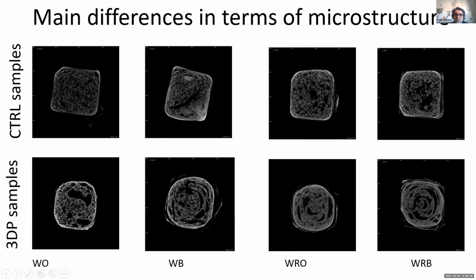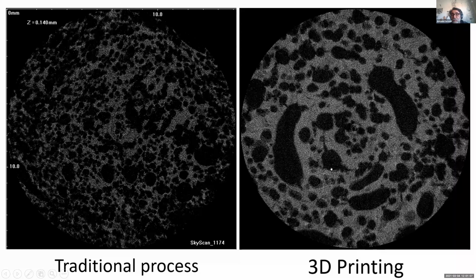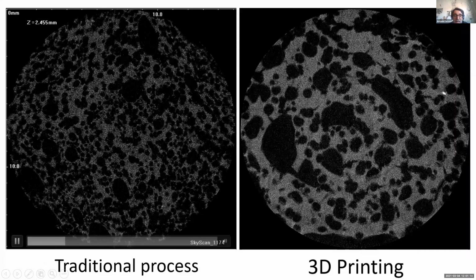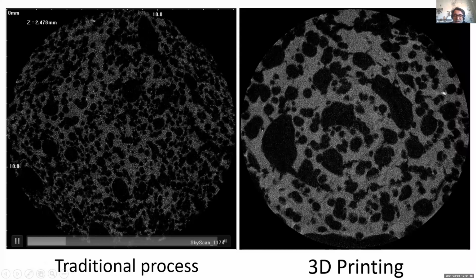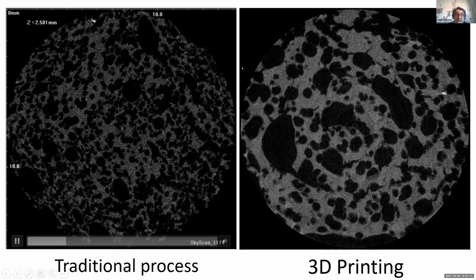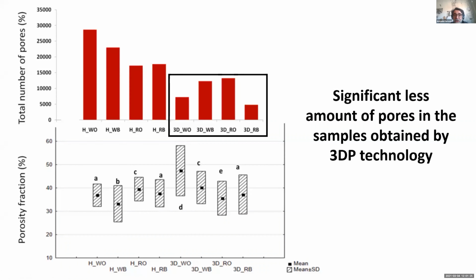You can see the control sample by hand. These are the 3D printed sample. It is very easy to observe the filament and the movement of printing, but this opens new fracture, and this has a significant effect on the texture property, the final texture property. I want to show you the differences in microstructure. We have a very big pore here, a very small pore here. So 3D printing also has a significant effect on the microstructure and on the number of pores. The 3D printed sample shows fewer pores in number, but big in shape and big in dimension.